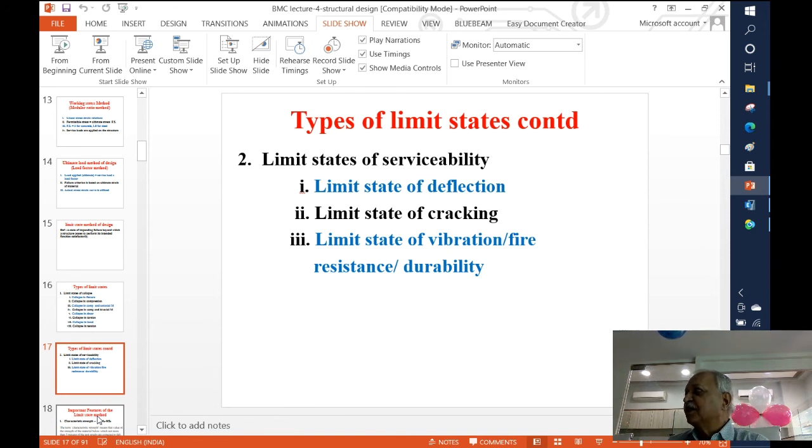So codes of practice indicates that you calculate the crack width and limit it to 0.1 mm or 0.2 mm depending upon the kind of application that you have got. If it is a very corrosive atmosphere in industrial structures where very poisonous gases are released, or gases which are harmful to reinforcement, then the crack width may be limited to even lesser value, and so on. So in case of a structure, its application and its surrounding, we say that it has got to be limited, the performance is to be guaranteed satisfactory.